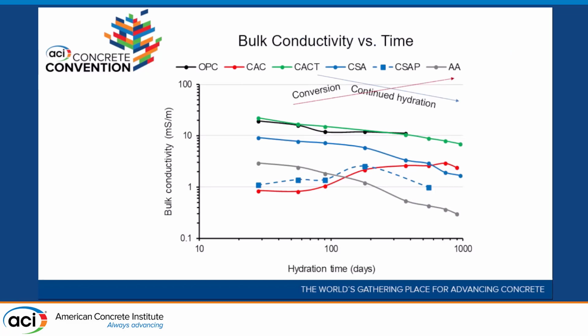We just looked at, realizing that bulk conductivity is in general related to the diffusion coefficient, we just measured that over time. You can see in general, of all the materials we tested, most of them came down in time. One of the CSAs stayed kind of low there, bouncing around, but all coming down. The only one that actually went up in our materials was the CAC, which was a calcium aluminate cement. Somewhere around 90 days or so, as we always saw on corrosion tests and everything else, it went through a phase transformation as far as we can say, and the values changed. But in general, long term, and you can see this after 1,000 days, we're looking at 3 years worth of data here.